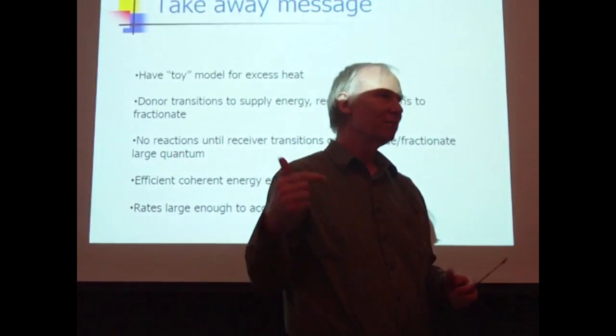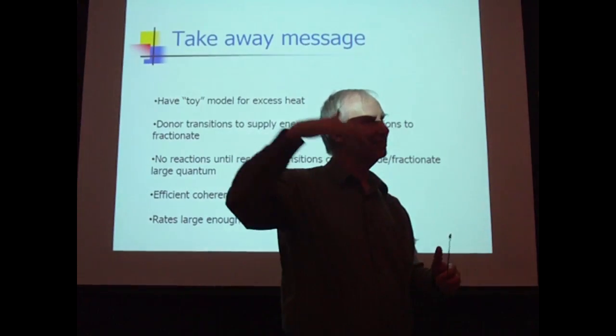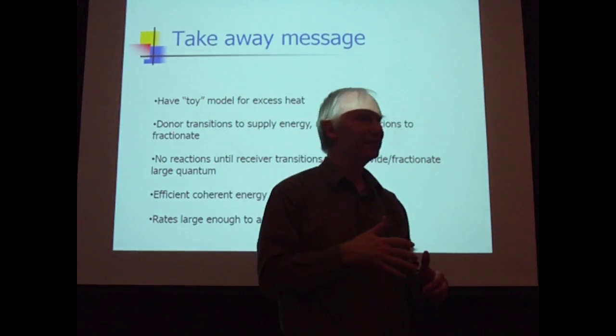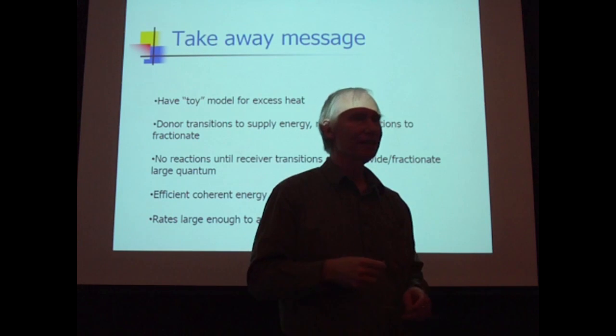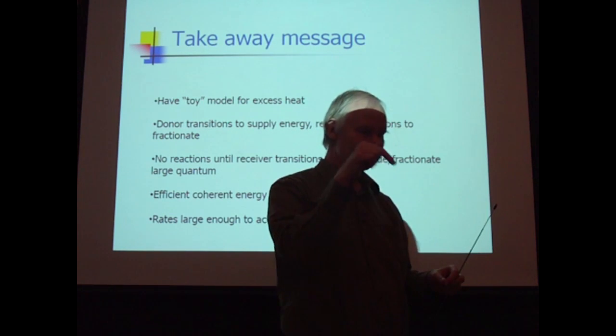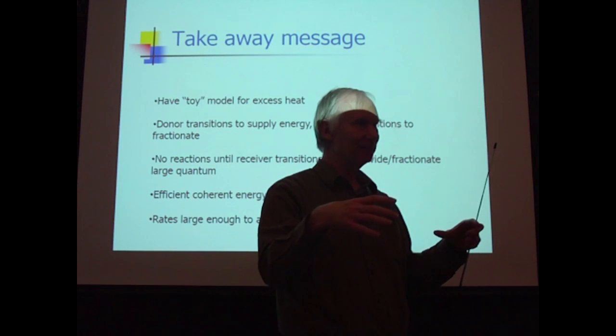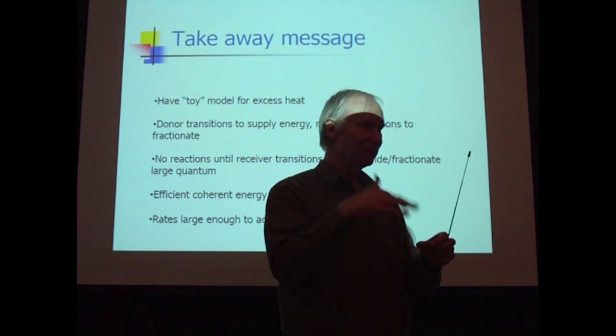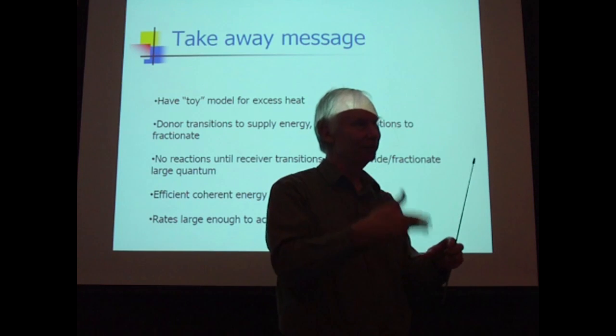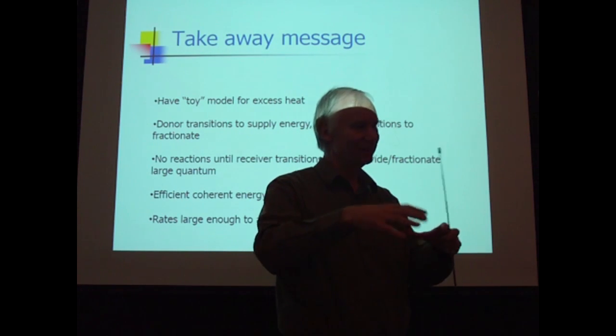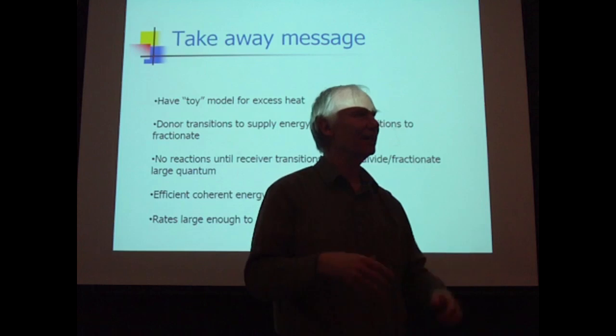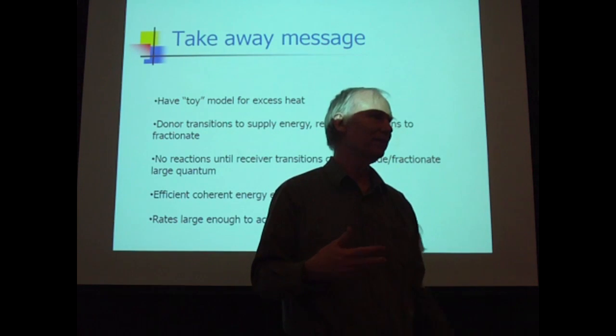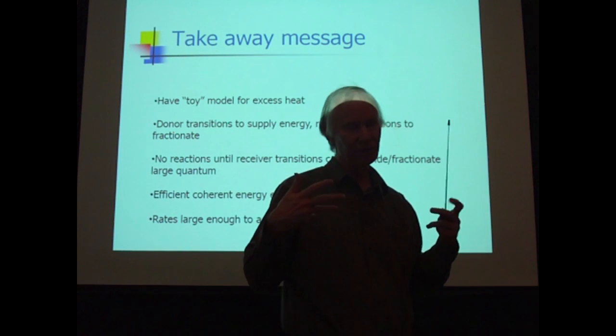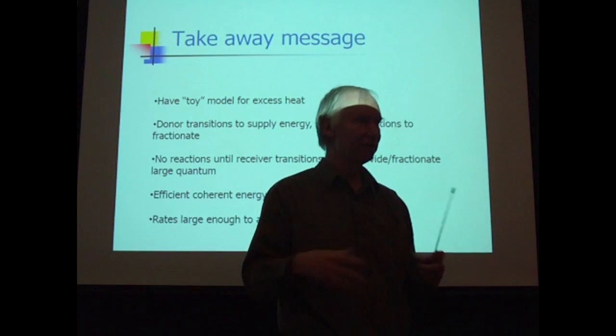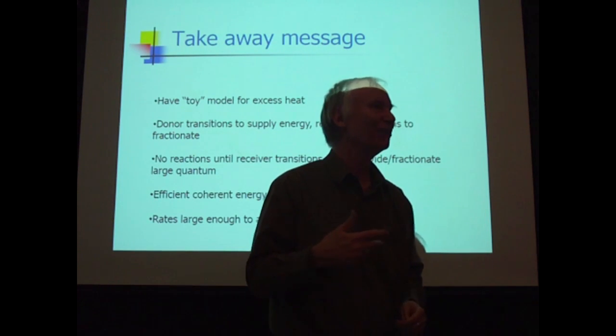In the LETS experiment, there's this dynamics. The laser turns on, the excess heat wanders up, and depending on which frequency difference he hits it takes different times to wander up. And I'm scratching my head, I'm thinking, well, laser is focusing down a millimeter, the thing's a centimeter. I'm actually thinking that what's going on is it starts out sort of doing its thing on a small scale, and then it spreads out, and eventually the whole thing's going. I think it's a little bit like a laser mode, that wherever coherent vibrations can be induced, they're going to be induced, the bigger the better, and the model likes more.